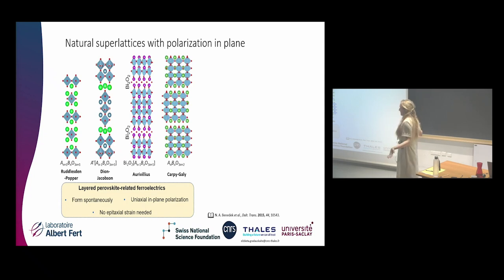So here we have different systems, Ruddlesden-Popper, Dion-Jacobson, Aurivillius, and Carpy-Galy, families that I'd like to introduce to you. You can see that they all have in common that there are these perovskite blocks of a variable number n, and they have some intersecting planes that create the special electrostatics. So it can be some rock salt layers, can be some additional alkali ions, or bismuth oxygen, or in the Carpy-Galy case, some additional oxygen planes.